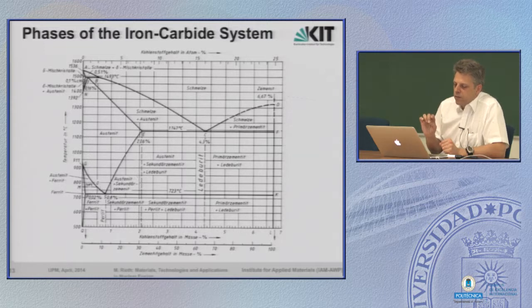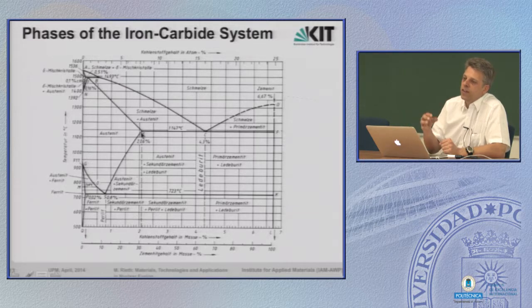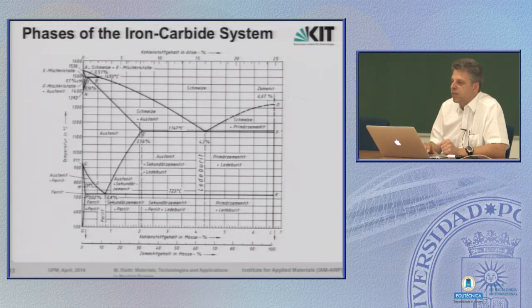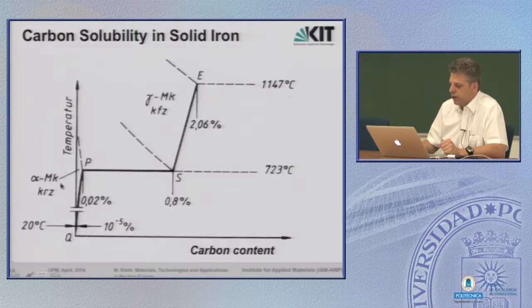What you can very easily deduce from such diagrams is the solubility, for example, in this case, for carbon in iron. You see here, this is the maximum content of carbon which can be solved in iron. That's about 2 weight percent carbon, which can only be completely solved at this temperature, around 1150 C, in the austenitic phase. If you cool it down, you have immediately decomposition, perlite formation, and compare it with BCC structured iron. Here we have a point with 0.02% carbon. That's the maximum content of carbon you can solve in the BCC structured lattice. This is important for the further consideration.